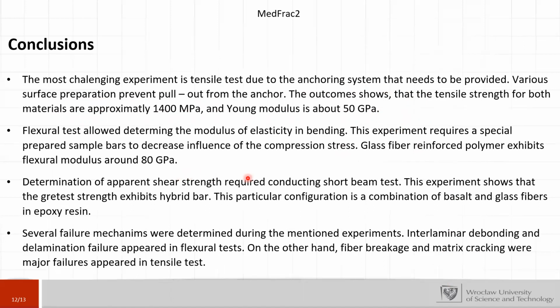The flexural test allowed us to determine the modulus of elasticity in bending. This experiment requires specially prepared sample bars to decrease the influence of the compression stress. And the glass fiber reinforced polymer exhibits a flexural modulus around 80 gigapascals. The determination of apparent shear strength required conducting short beam tests, and this experiment shows that the greatest strength is exhibited by hybrid bars, so the basalt and glass fiber. This particular configuration is a combination of basalt and glass fiber in epoxy resin.